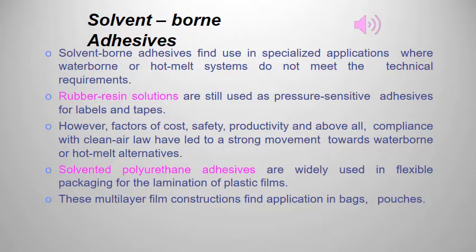Once the adhesive is applied, solvent evaporates relatively quickly, causing an increase in the viscosity of the adhesive film. Bonds can be made immediately after adhesive application or after some solvent has evaporated, but before the adhesive has dried to the point where it will no longer wet — this is called the open time. Waiting for some evaporation prior to bonding, called set time, increases the initial bond strength and allows assemblies to be processed more quickly.